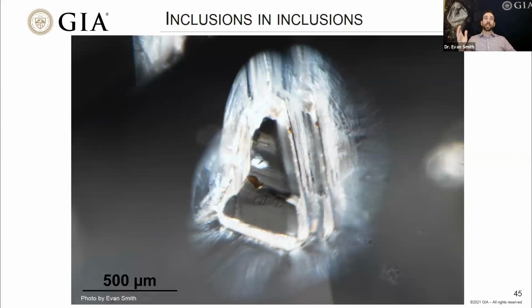So sometimes we not just see inclusions, but we see inclusions inside inclusions. Sometimes we don't just trap a single mineral grain, but for instance, in this case here, we've got an olivine inclusion. It's this colorless material around here. It's a pretty big inclusion. And then right in the middle of this olivine inclusion, we see this region of brown color. And this is actually magnesiochromite. So this little brown piece is probably a piece of magnesiochromite that existed within the olivine, and then the whole thing was trapped inside this diamond. So this doesn't happen all that often, but it does occur.